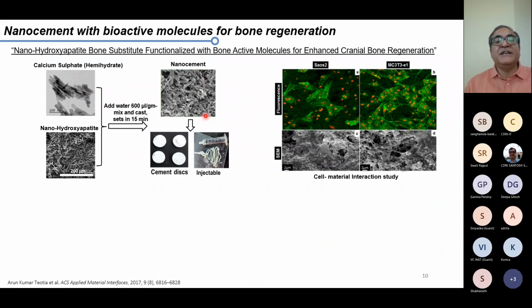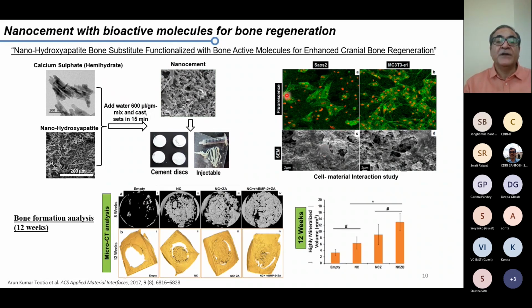So this is the same image which you will see after it sets like a cement, but it can be injectable, as you can see in this picture. We have seen that it is osteoconductive. We have been able to grow both SaOS-2 cells and pre-osteoblasts here, and you will see both by staining or by fluorescence here. Then I'm immediately coming to the rat model, where we have a cranial defect. At 12 weeks, we have an empty cranial defect of about 8 mm size, which is considered critical in the rat. This circular part is the defect. Then if you fill it only with the cement, you simply put it at the defect site.